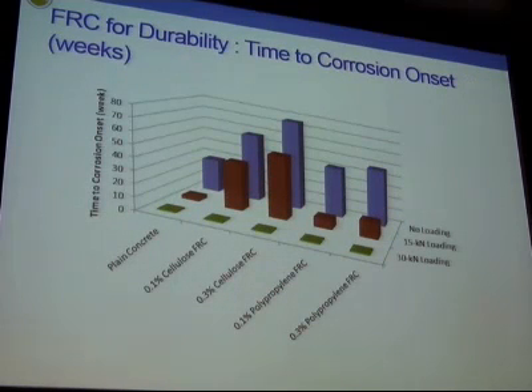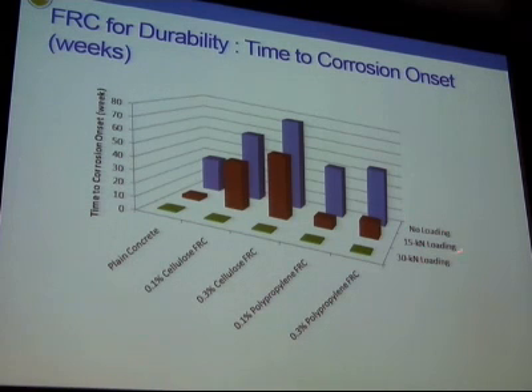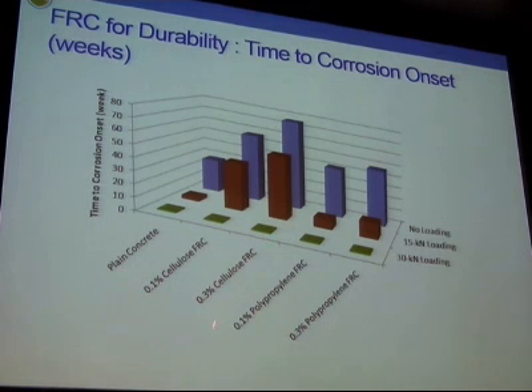So when you're using fiber-reinforced concrete, and this is the other study we performed, we looked at time to corrosion as a result of use of fiber-reinforced concrete in the structure. And here are 3 elements. One is unloaded, one is 15 kilonewton loading, and one is very close to 30 kilonewton loading, which is very close to the capacity. As you can see, if I'm using plain concrete, 0.1% cellulose fiber, 0.3% cellulose, 0.1% polypropylene, and 0.3% polypropylene, you will notice that as I'm increasing the fiber content under one loading, the time to corrosion actually starts to increase, which means I can now derive a lot more from the structure before the corrosion actually takes over.